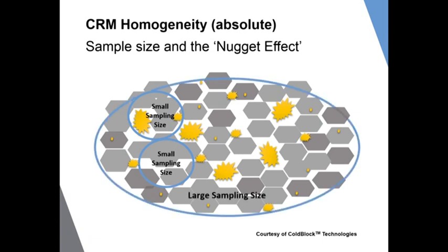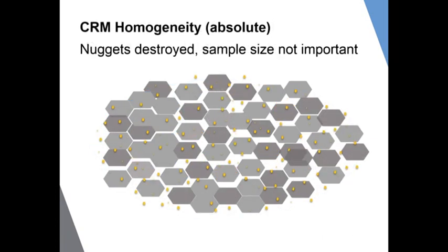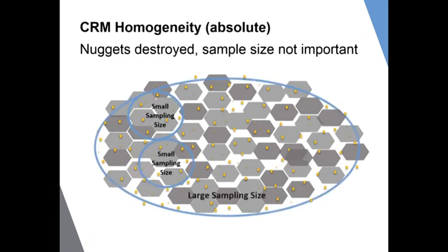The way to quantify this is to induce a sampling error and then scale that result using the known relationship between standard deviation and sample size to a more practical context, which could be 30 grams for a fire assay. And we do this for every gold CRM we produce. We do it by sending 20 samples for neutron activation analysis standardized on an 85 milligram aliquot. So that's very small indeed.